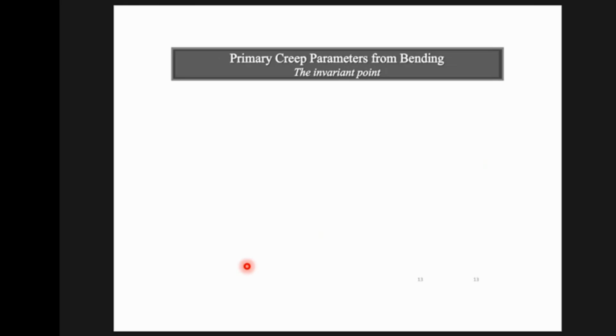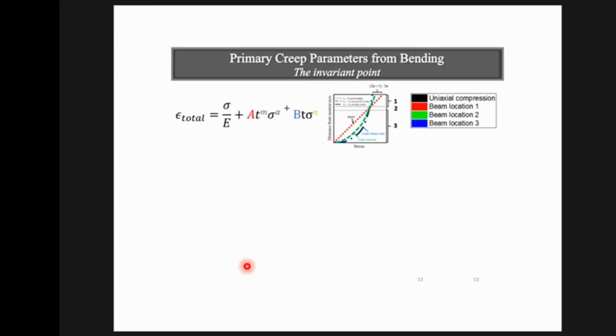Now that's as far as steady state creep goes. Now, when you have primary creep, we know that the creep rate is changing with time. The exponent that relates stress and strain rate may not be the same as what it is in steady state. But nevertheless, it turns out that when you watch the stress state change from the linear behavior to the redistributed shape, there is one point here at which all these lines cross, more or less irrespective of what the stress exponent is. So by now you'll have got that the shape of the stress distribution across the beam depends on n, the stress exponent.